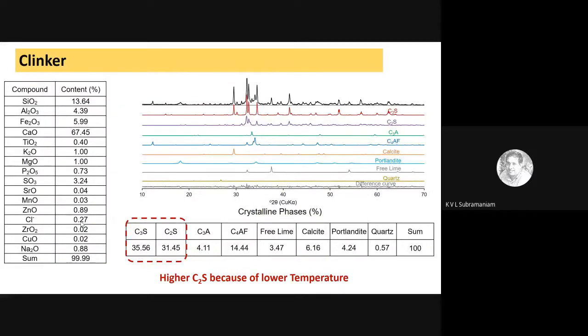And then the clinker that we produced from the vertical kiln. When we did the chemical composition analysis of this, basically we were able to form tricalcium silicate and dicalcium silicate. And because there was also alumina and iron present in the source materials, we also formed tricalcium aluminate and also tetracalcium aluminoferrite, the 4 Bogue's compounds. One has to remember that C3S, C2S, C3A and C4AF, the 4 primary ingredients of cement, are crystalline compounds.